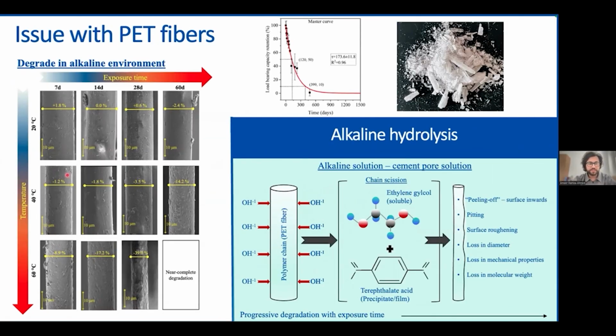Here, for example, you see on the left-hand side a study that we conducted where we put PET fibers in an alkaline solution of 12.5 pH for different durations. Here you see on top 7, 14, 28, and 60 days. And we also wanted to accelerate this degradation, so we also did this for different temperatures: 20, 40, and 60 degrees. What these SEM images show is a very clear degradation of the PET fibers as the temperature or the exposure time is increasing.